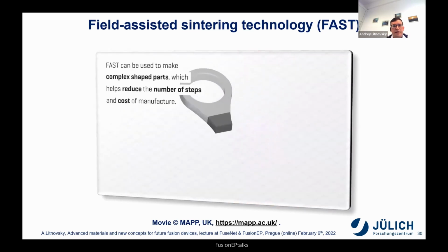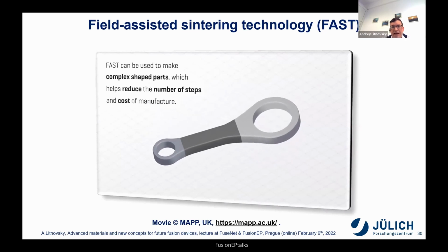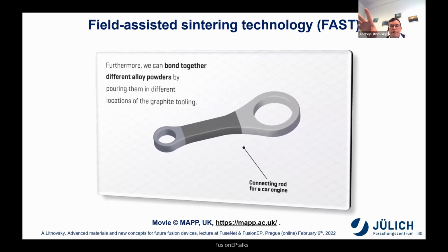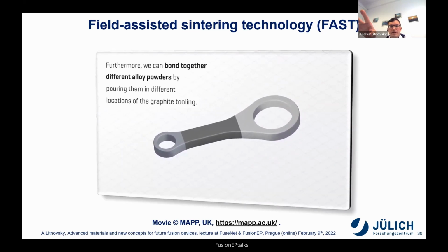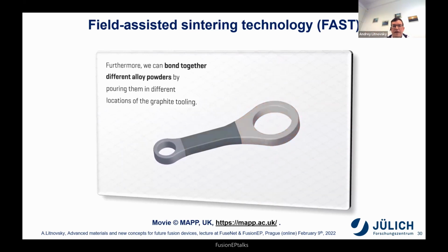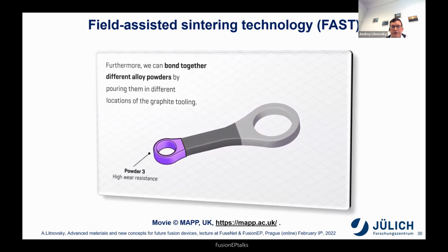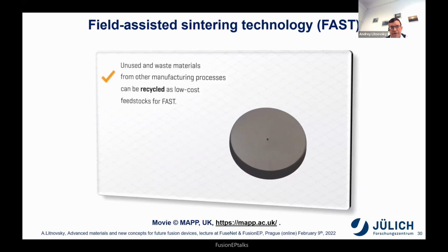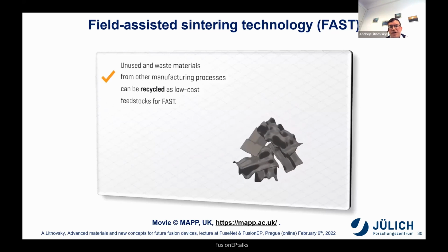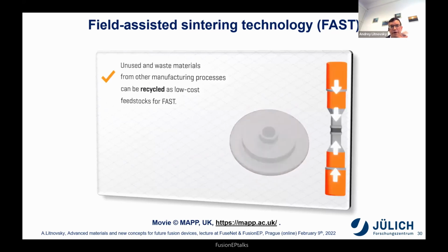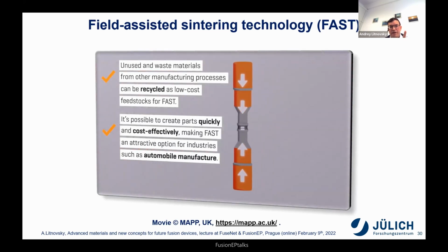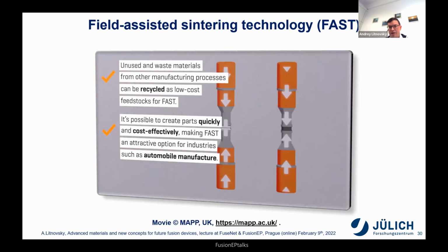And finally, it results in spectacular features, like making materials with very different properties and characteristics within one sintering technique. But the most important effect is the low cost and tremendous speed of such sintering. You can imagine, our smart alloy is sintered in an entire process of 15 minutes, but the sintering itself takes only 7.5 minutes, and another 7 or 8 minutes are for cooling.